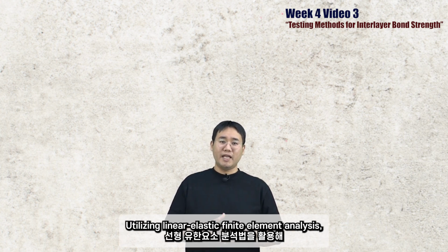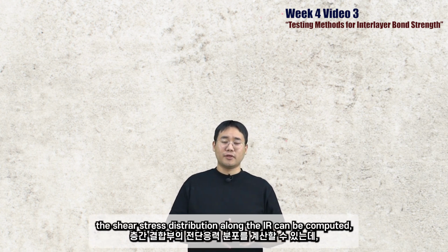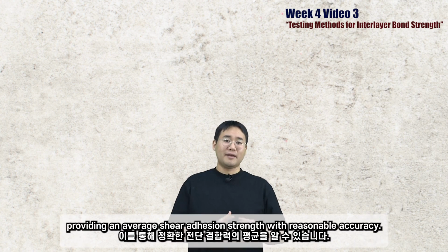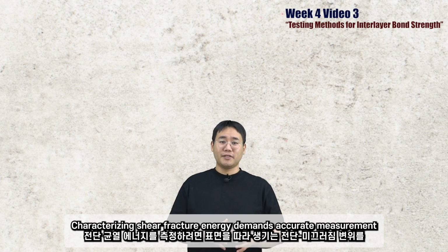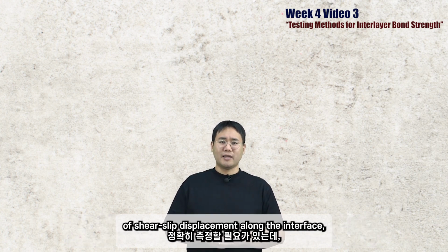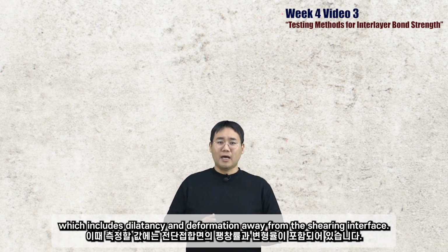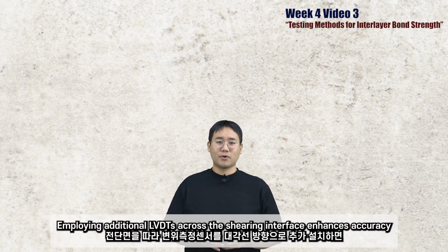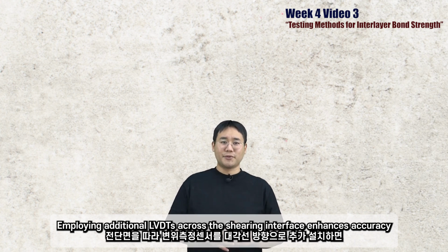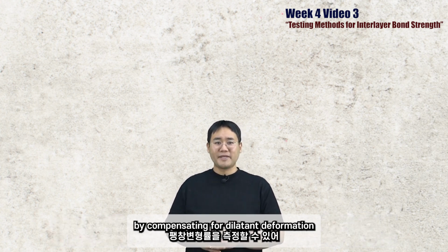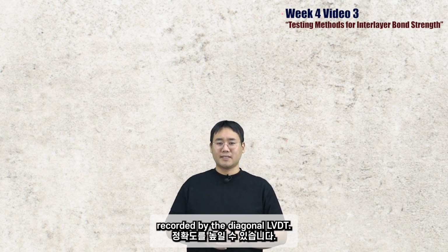Utilizing linear elastic finite element analysis, the shear stress distribution along the interlayer region can be computed, providing an average shear adhesion strength with reasonable accuracy. Characterizing shear fracture energy demands accurate measurement of shear slip displacement along the interface, which includes dilatancy and deformation away from the shearing interface. Employing additional LVDTs across the shearing interface enhances accuracy while compensating for dilatant deformation recorded by the diagonal LVDT.